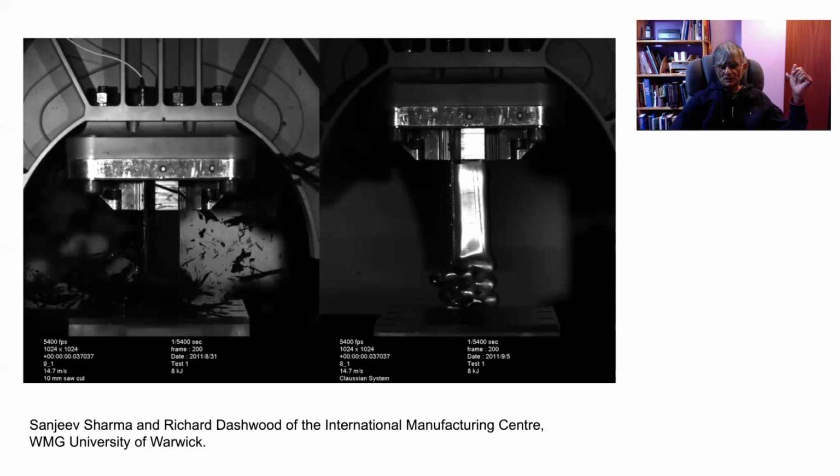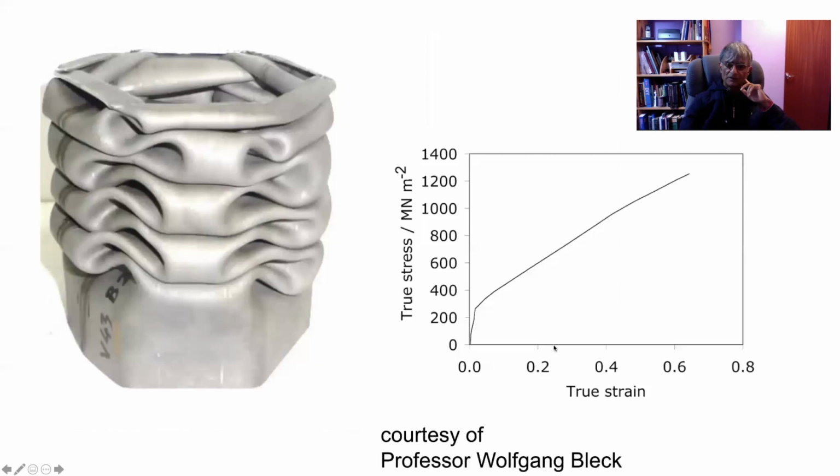Now, obviously, steels with a large amount of area under the stress-strain curve might be good candidates for this, okay? But the problem is that the strength is really achieved only after quite a lot of deformation. Whereas if you had a curve like this, you would absorb much more energy. So this level of deformation only occurs in these regions here. And that means that it's not actually effective in absorbing energy, because the deformation is very localized instead of uniform throughout the sample.